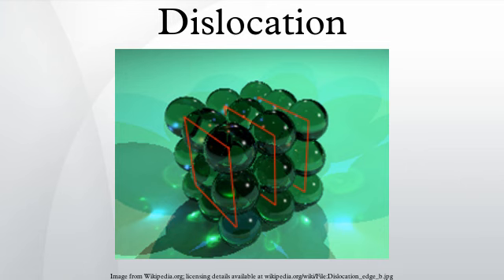The surface of a crystal can produce dislocations in the crystal. Due to the small steps on the surface of most crystals, stress in some regions on the surface is much larger than the average stress in the lattice. This stress leads to dislocations. The dislocations are then propagated into the lattice in the same manner as in grain boundary initiation. In single crystals, the majority of dislocations are formed at the surface. The dislocation density 200 micrometers into the surface of a material has been shown to be six times higher than the density in the bulk.